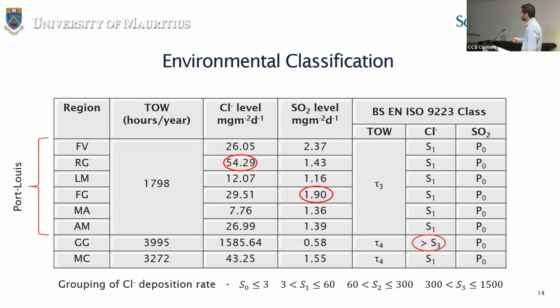However, there's a marked difference between the chloride deposition rates measured from these sites, with the highest value observed at RG, and this is very close to the upper limit of that category. It is also interesting to note that the chloride deposition rate of MC, which is the mid-island atmosphere, is higher than all the sites in Port Louis except RG. And MC and GG have a high TOW, time of wetness, compared to Port Louis.